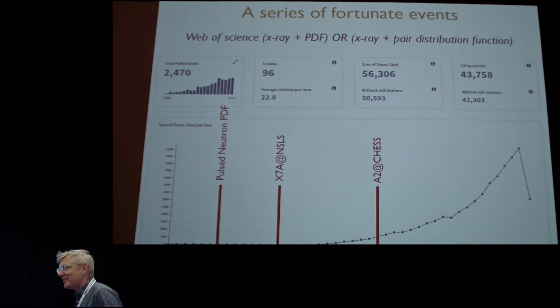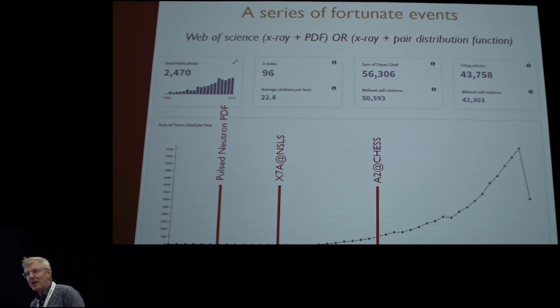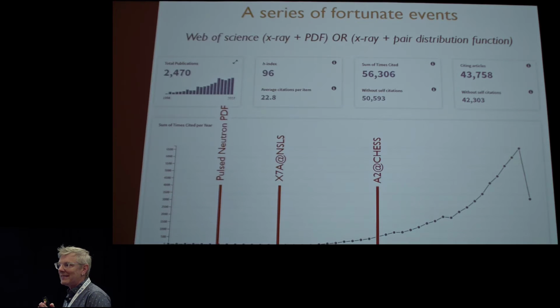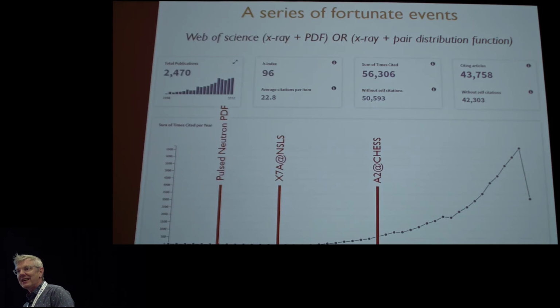A limitation of the X-ray sources that we had at the time was that they didn't have very high energy X-rays, so they didn't have short wavelength X-rays, which limited the Q range we could measure, which limited the real space resolution. I was now an assistant professor at Michigan State, and I was very anxious to resolve the difference between an indium arsenic bond and a gallium arsenic bond in a semiconductor alloy. I thought I was going to do it with pulse neutrons, but I was naive. It turns out there's this neutron resonance which prevents you doing that experiment.